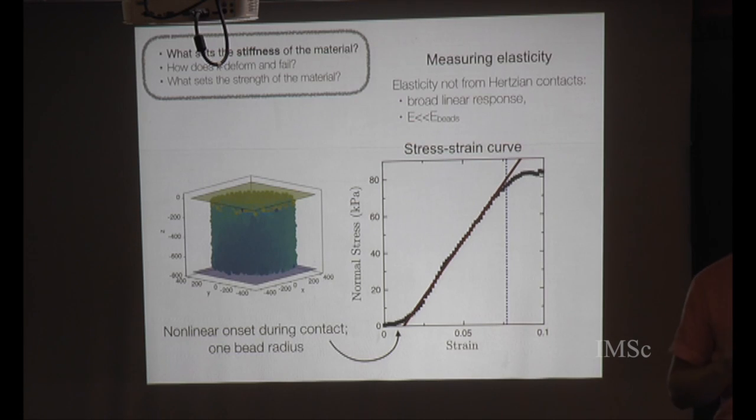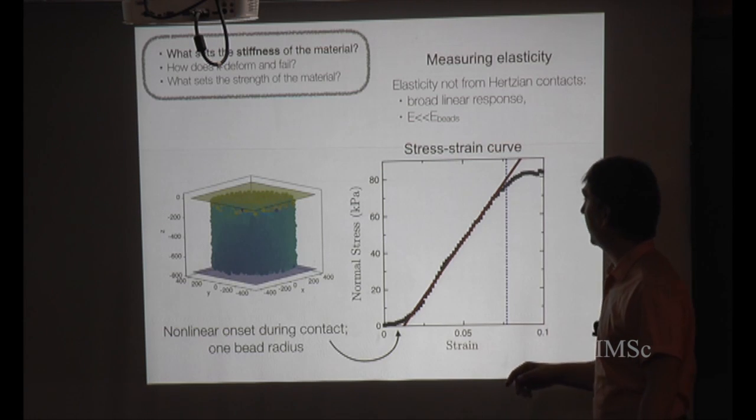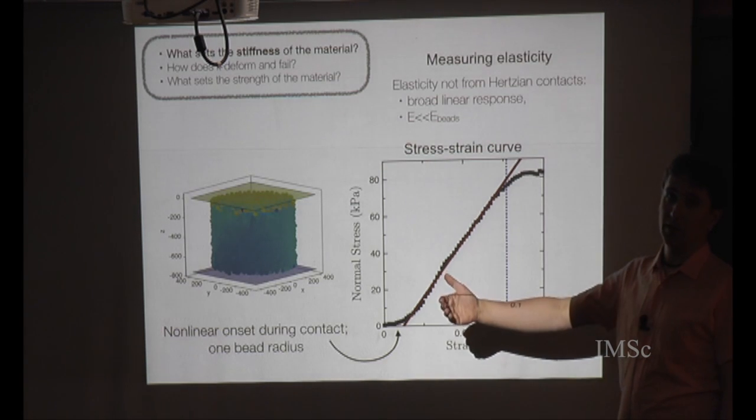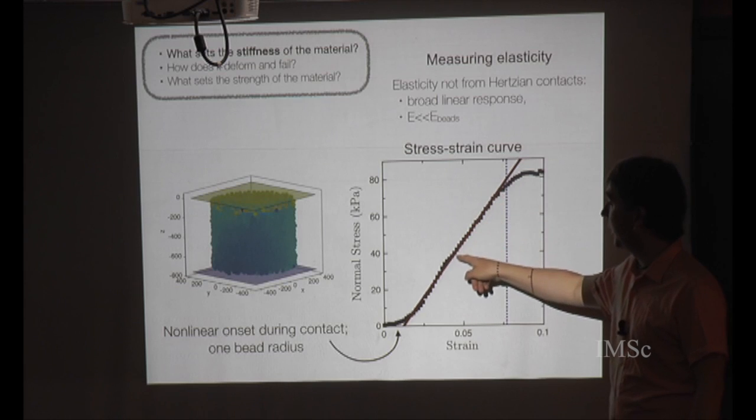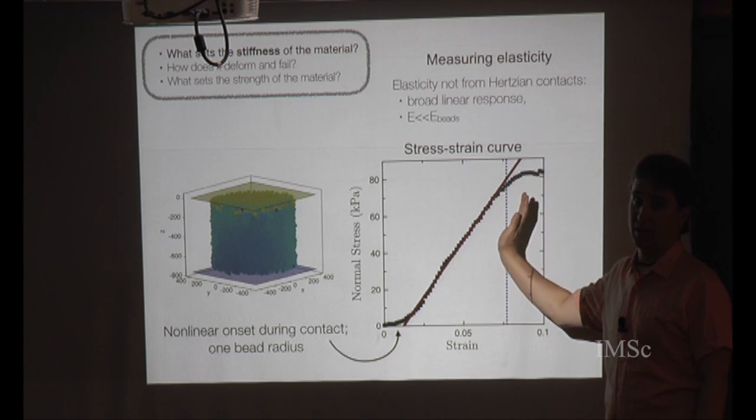At the back as well. So, in this elasticity, if you just compress the material and release it, will it come back to the original shape? Yes, there is a small amount of hysteresis, which depends on how quickly you do it, but we are in the limit where if you measure a back response, it will be the same slope.